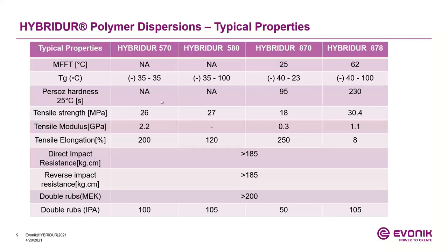And if you look at the impact resistance of all the Hybridur polymers, they offer greater than 185 of impact resistance, and also provide outstanding MEK double rub resistance, as I showed before. Outstanding MEK double gives greater than 200 MEK double rub resistance. And they have excellent elongation. For example, 570 has elongation of 200%, 580 120%, 870 is about 250%. So these polymers are very robust, have excellent flexibility, provide outstanding impact resistance, both the reverse and the direct impact resistance, and outstanding solvent resistance.